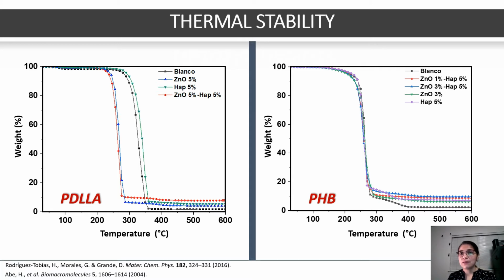Unlike PDLLA, the thermal stability of the PHB ternary system was not significantly affected by the incorporation of nanoparticles. Just a slight decrease in the degradation temperature was presented in relation to the blank.